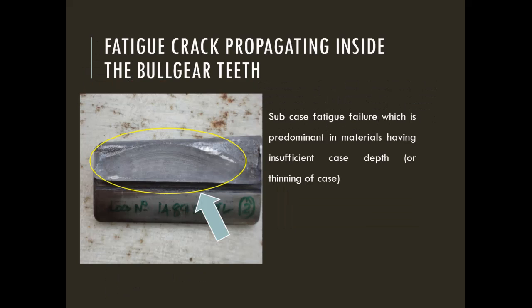This is a subcase fatigue fracture — a different type. This is a gear tooth whose surface is hardened to around 55 RC. Because the surface is very hard, the fatigue crack starts propagating inside the component rather than from the surface. This is called subcase fatigue, and it often goes unnoticed without the knowledge of the maintenance personnel.